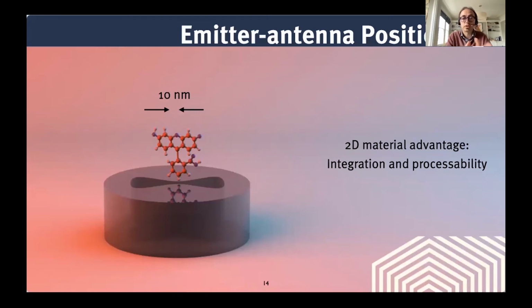So to actually exploit this antenna, we need to put our emitter inside that little gap. And this is very hard to do with a molecule, because nanopositioning is really difficult. But this is instead something that we are trying to explore with the use of 2D material, because in this case, the 2D material can be designed to go conformally over these antennas, or we can even create a local defect at the position of the gap. And you see, the 2D material for us in photonics doesn't come as just another emitter. It's a different family of emitter, which we can manufacture and engineer and play with in a different way.